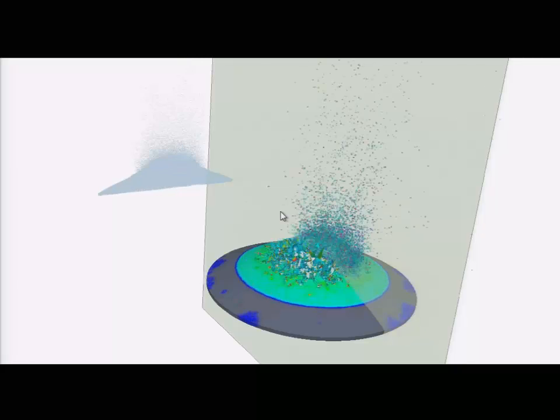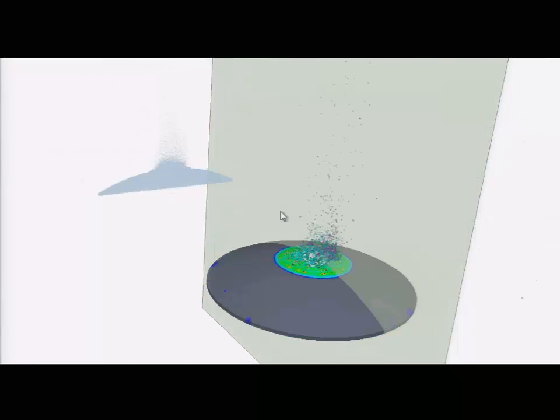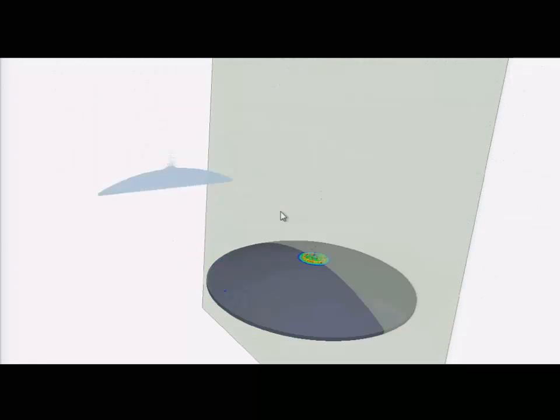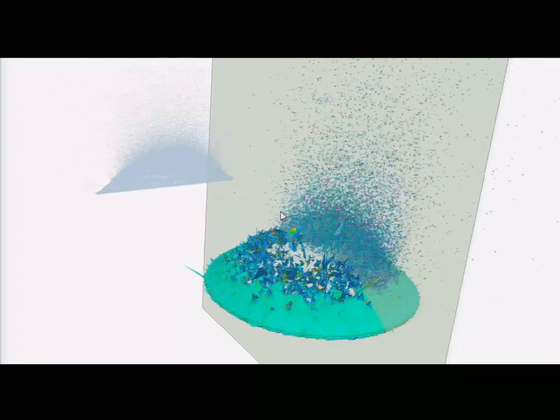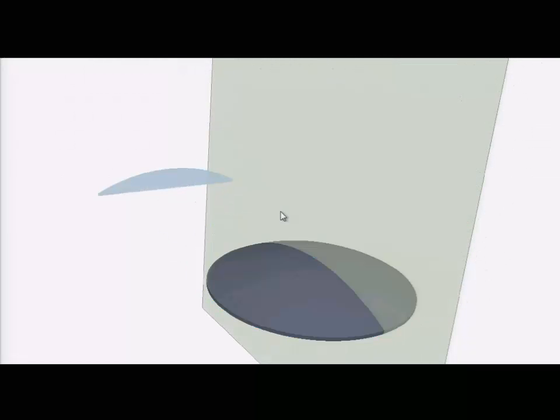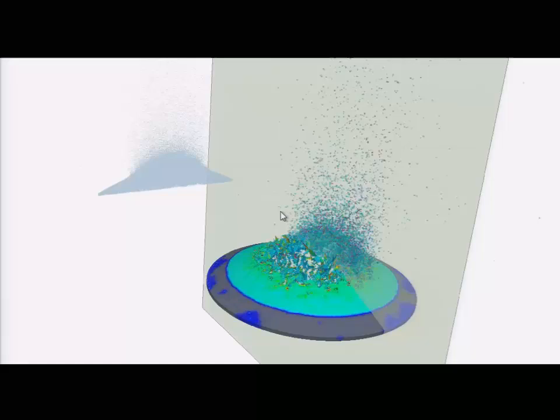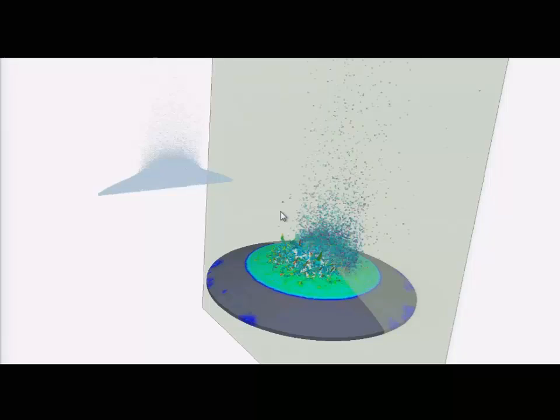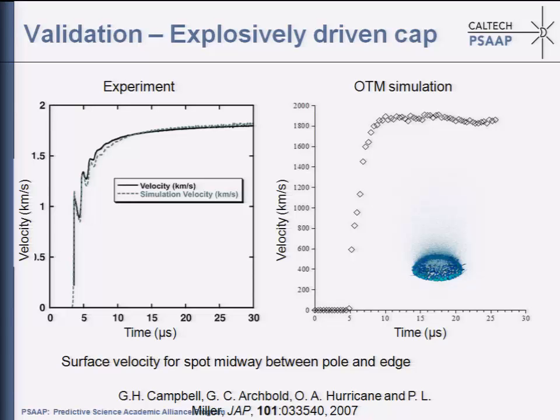So you have, again, a spherical shell, and in this case we just apply a simple drive that models somehow the detonation. You can see here the formation of very fine fragments. We do this with a material point method, so the way we model fracture and fragmentation is specifically by failing material points. And what the multiscale model tells you is exactly when you have to fail a material point. You can see that away from the center of the shell you have fragments that are much larger in size.